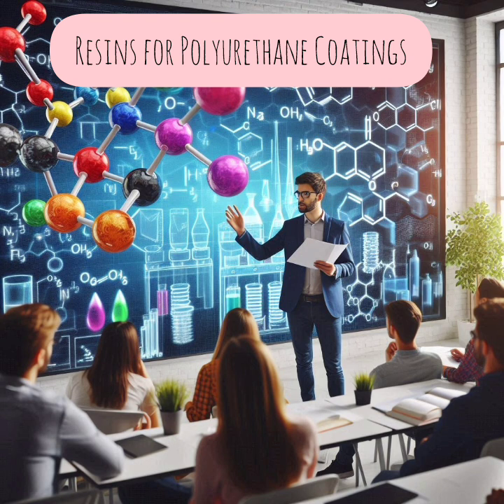Two-pack systems. The most popular and widely used two-pack systems are based on hydroxyl functional resins and isocyanate adducts. They cure at ambient temperature to provide a tough, solvent-resistant film. The hydroxyl functional resin may be an alkyd, polyester or acrylic polyol. The isocyanate adduct may be an aromatic toluene diisocyanate (TDI) or an aliphatic hexamethylene diisocyanate (HMDI), which is made as an adduct with alcohols or phenols such as trimethylol propane, propylene glycol etc.